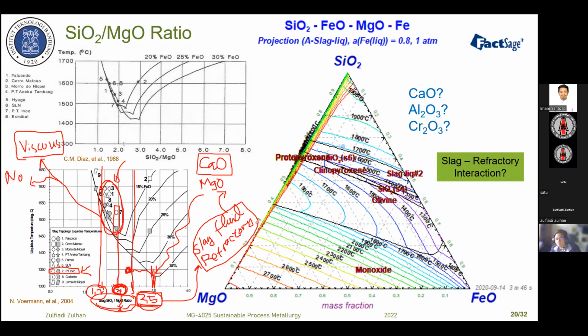And then the other plants, if they do not use any copper cooling in the furnace, also add CaO to increase the surface life of the refractory material. Two things should be considered. The first one is the silica to magnesia ratio. The other is iron oxide. This iron oxide is also very, very aggressive to the refractory materials.